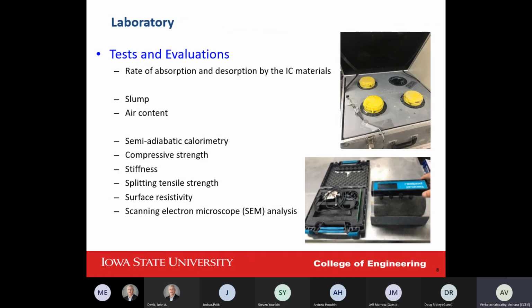And we've done some lab tests and evaluation for slump and air content. Calorimetry means we record the temperature of the concrete for the first month, 30 days or 28 days, so we can measure and evaluate the hydration that is going on, because hydration causes higher temperature. Also compressive strength and stiffness, split tensile strength, surface resistivity, and also SEM, which means we cut the samples and scanned them, did some image analysis, and compared the non-reacted cement together.